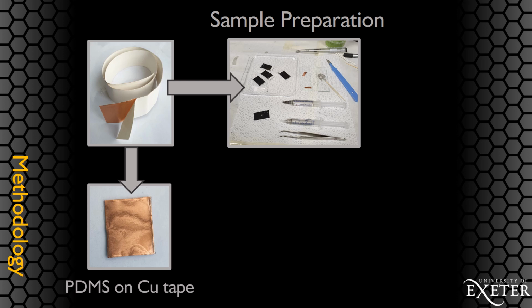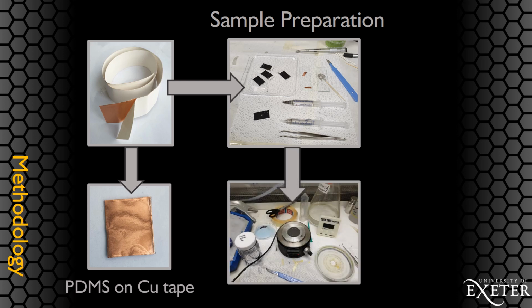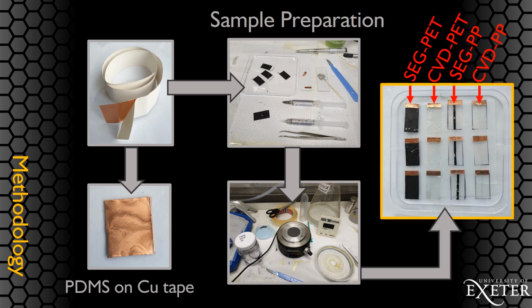the circuit. After a quick dry in the oven, all samples were spun coated further with PMMA to reach a thickness of 800 nanometers. This meant 1 coat for CVD samples and 2 coats for SEG. A swab of warm acetone then removed any PMMA on the copper contact. And then the devices are now ready. 3 of each configuration were produced in order to isolate potential anomalies when characterization was underway.